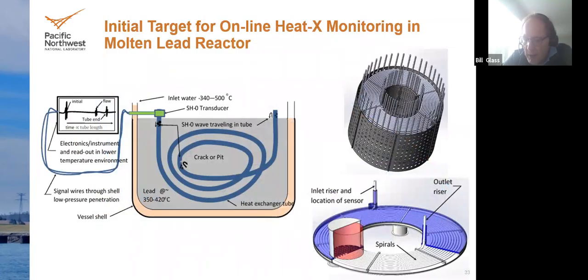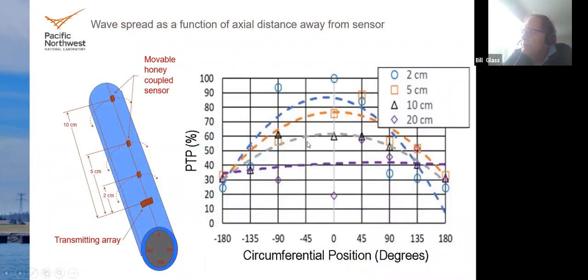So we also, excuse me, wanted to confirm that we could have a relatively small section of the tube that would be instrumented with the array of sensors. And so we did a test where we had the array here over a small portion of the tube, and then we moved a sensing element first axially, like 2 centimeters, and then 5 centimeters, and then 20 centimeters down the tube, and then moved it circumferentially all the way around the tube.